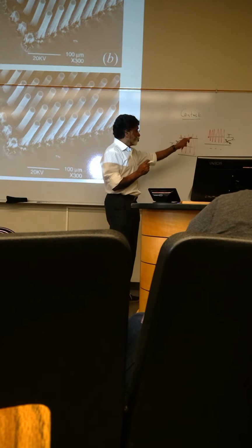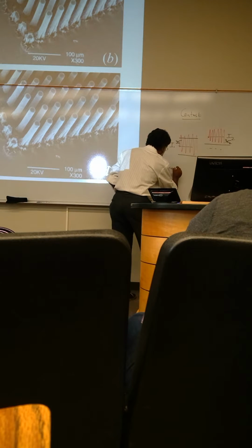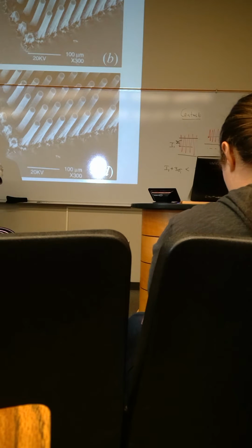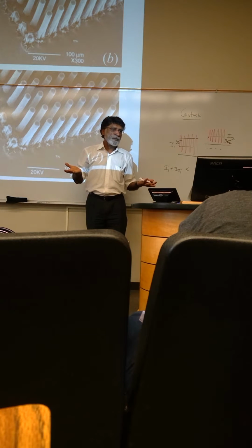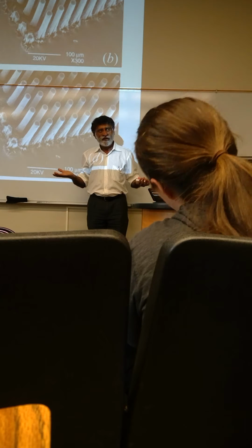So strictly speaking, for you to see a difference between the two areas, I1 plus 3 sigma 1 should be smaller than I2 minus 3 sigma 2. Correct? In the sense, the signal goes from here to here, the signal drops from here to here, and they should be resolved separately. Otherwise you don't get a signal. You don't get a good contrast. Everybody with me?